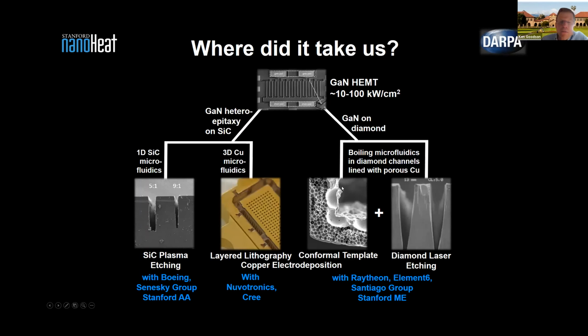If you bond, however, to diamond, you have a marvelous opportunity to make an incredibly effective, albeit very expensive, heat sink made from diamond. So with diamond, you can etch the channels, and Raytheon had developed etching technology, and so we actually pumped the fluid through diamond, and to make the situation even more aggressive, we coated the diamond with microporous copper that would facilitate the phase change heat transfer. So we made prototypes and tested them in all of these paradigms with DARPA support.